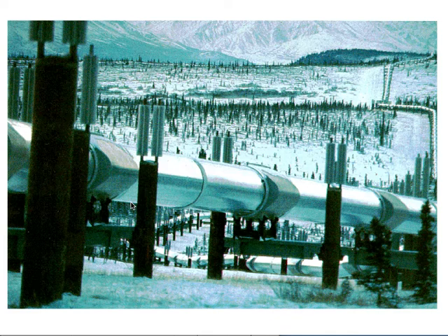So it's huge technology actually, because if you get fracture, then the fracture can propagate for kilometers, because the plastic zone is effectively several meters long. So these are absolutely spectacular tests. You take a long pipe, you seal it from both ends, and then you overpressurize to see whether this crack will actually stop in a certain distance. So you effectively blow up these pipes. It's fantastic to see.